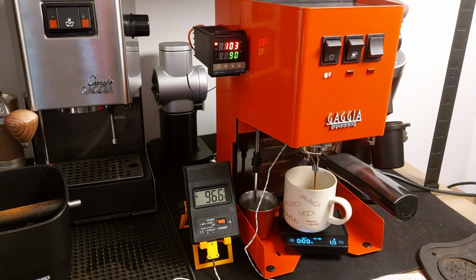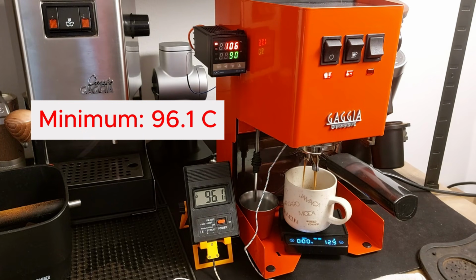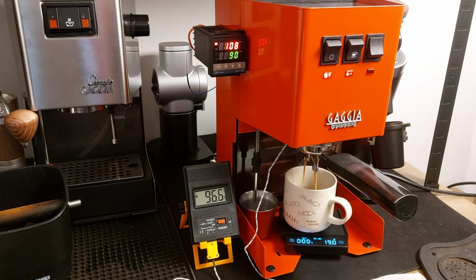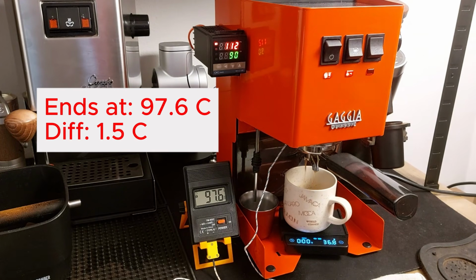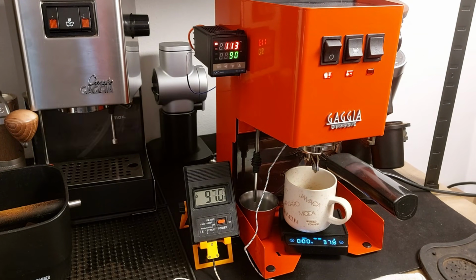So when the light goes off, the temperature starts at 97.2 degrees, it decreases to 96.1, and then it goes up back again to 97.6. So it's just 1.5 degrees difference between the maximum and the minimum. In this test, I extracted 38.3 grams in 27 seconds, but the result is amazing, super stable, equivalent to the test that I did with a PID in my Rancilio Silvia.